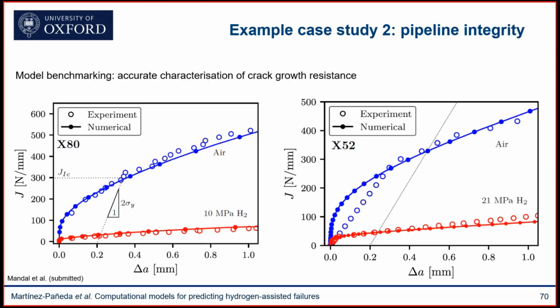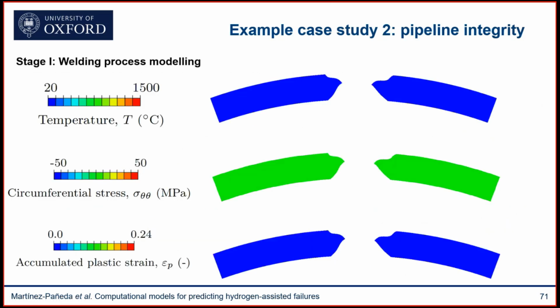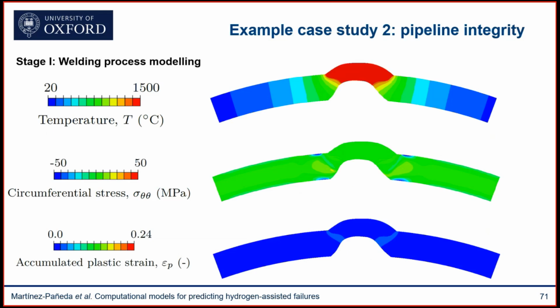And first things first, we want to make sure that the model works well, that the model is able to capture, for example, the plastic dissipation you get when you have sustained crack growth. So we've simulated the crack growth curves for the two materials that we're interested in here, which are X80 and X52 pipeline steels. And you can see that we get a very good agreement with experiments both in air and at various hydrogen pressures. So with this model that we trust and that seems to predict quite well the fracture resistance of metals, we first conduct those welding process simulations.